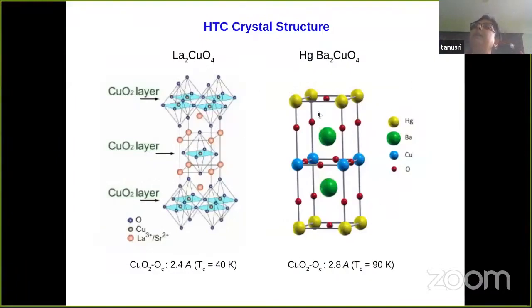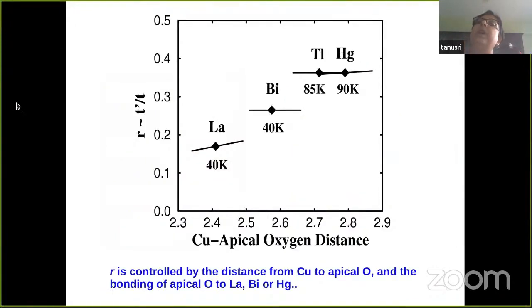Now, if you really look at the crystal structure of these two compounds, this is what I was mentioning, that you have a copper oxygen plane, but you have some out-of-plane oxygen, and that is what we call the apical oxygen. And the distance between the apical oxygen and the copper oxygen plane is quite different in these two compounds, being 2.4 angstrom for the lanthanum compound and 2.8 angstrom for the mercury compound. Plotting this range parameter R against this structural parameter, namely the copper oxygen plane to the apical oxygen distance, you do see a kind of dependency. So this R is controlled by the structural parameter, the distance from copper to apical oxygen, and the bonding of this apical oxygen to these out-of-plane orbitals.